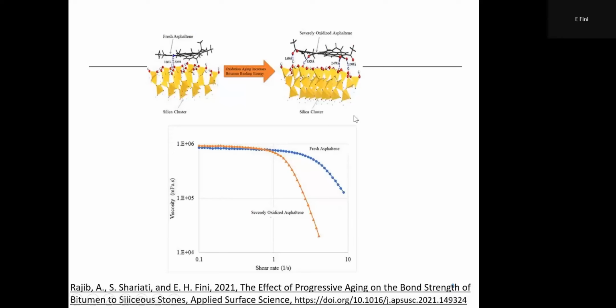And that's maybe a reason when you actually recycle asphalt, you get all these black rocks that have a very thin layer of asphalt completely coating the surface. Over time, they actually bonded pretty well as they oxidize. So here we show that oxidized asphalt can adhere or bond better to the surface of minerals, in this case silica-based minerals, like quartz.